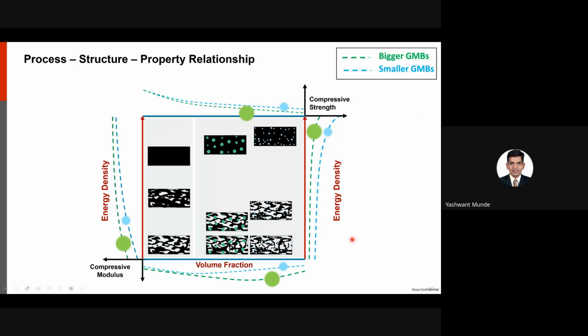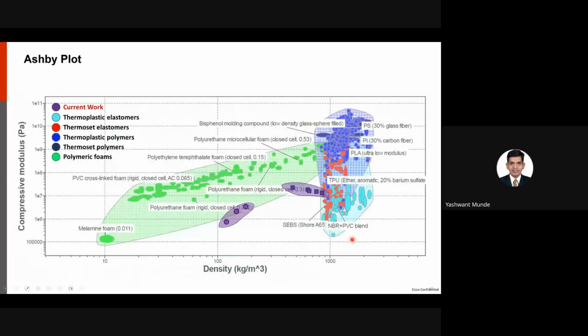Now, with all this said, how do these foams perform in the grand scheme of things? Here's an Ashby plot of compressive modulus to density. We did not compare strength because everyone has different ways of picking the compressive strength. Some may use a plateau strength, some may use the densification stress as the compressive strength. So we did not do that. Instead, we focused mainly on the modulus part.